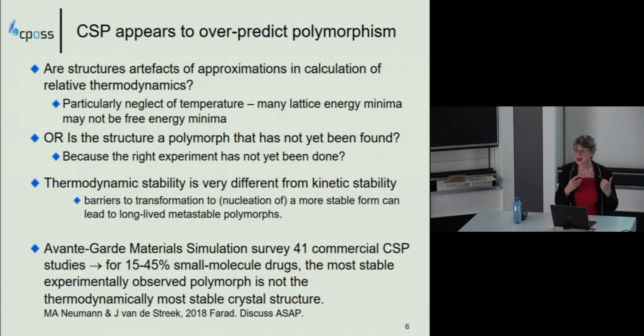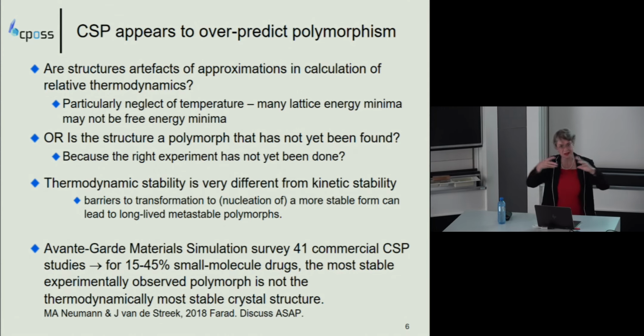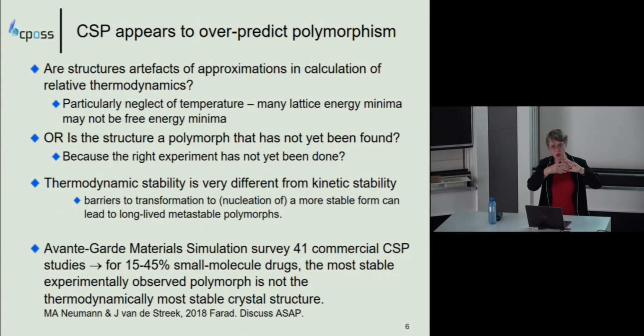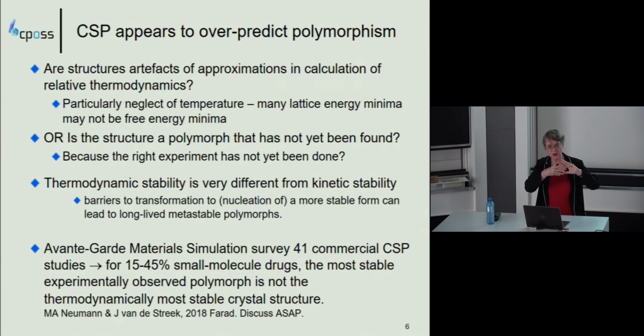Then the other alternative, which the industry is interested in, is a polymorph that has not yet been found because the right experiment to do it has not yet been performed. So thermodynamic stability is very different from kinetic stability. Once you've packed into the crystal structure, and if you can imagine these awkward shaped molecules, it can be very difficult to transform to another more thermodynamically stable crystal structure once you're packed.